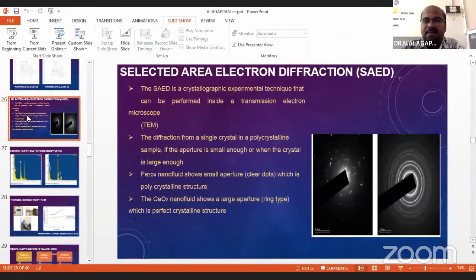So selected area electron diffraction. This is also one of the characterizations. SAED is a crystallographic experimental technique that can be performed inside a transmission electron microscope. The diffraction from a single crystal in a polycrystalline sample, if the aperture is small enough, when the crystal is large enough. So for the Fe3O4 nanofluid, the aperture is small, which means the structure is polycrystalline, shown in the figure.